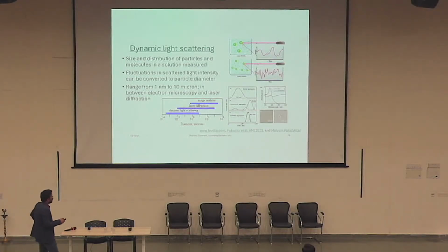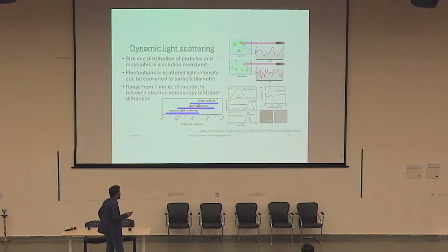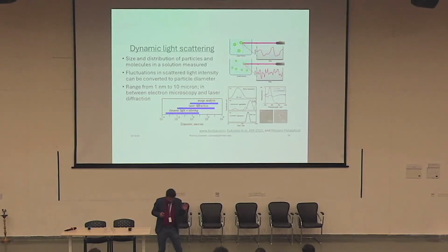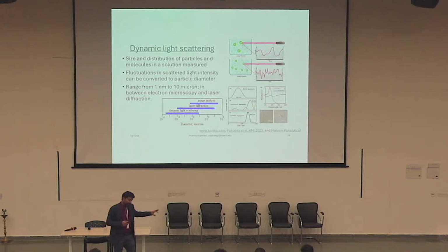And essentially what you get is this sort of profile, and the fluctuations in the profile you can use and convert towards a size distribution. So here your range is 1 nanometer to 10 micron. So it goes finer than your typical laser diffraction, but not as fine as electron microscopy.